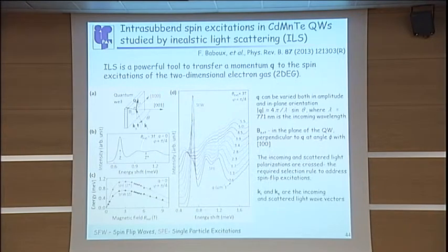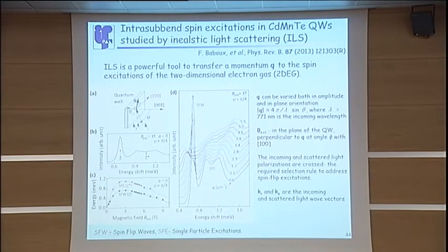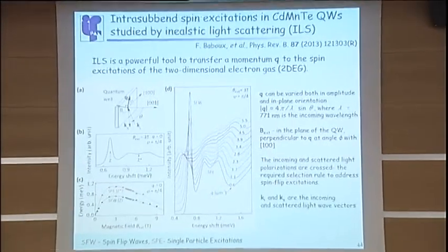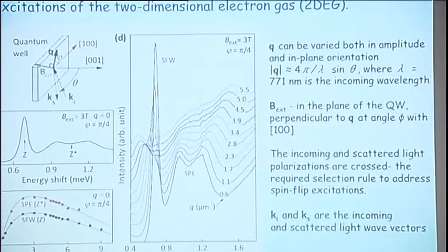So they have used an inelastic light scattering experiment, and please note that they have the peak from spin flip waves and also single-particle excitation. This is very sharp, which means that you have a single collective spin-orbit field, and these two shoulders represent the spread in the K.